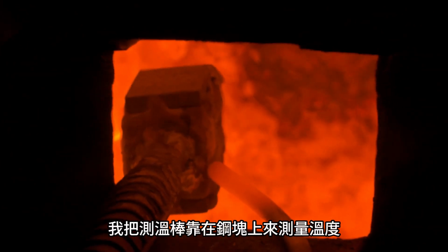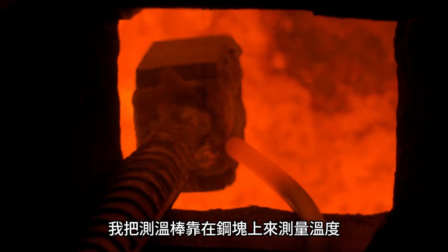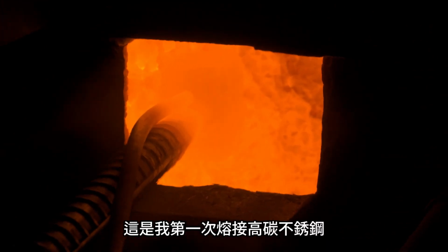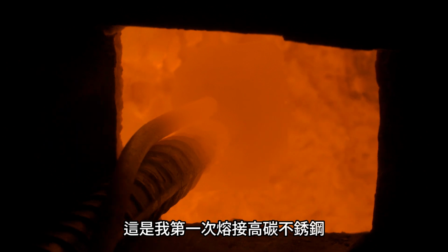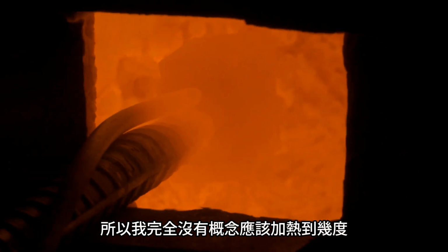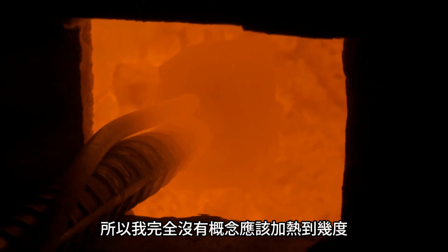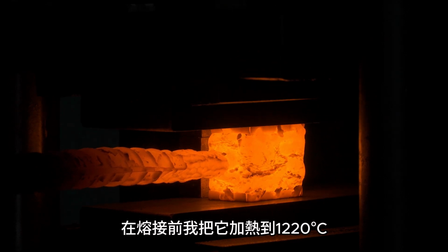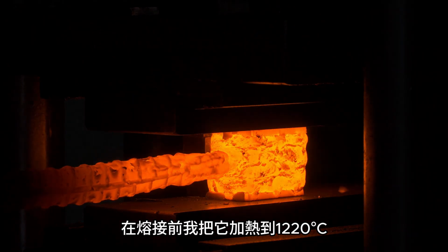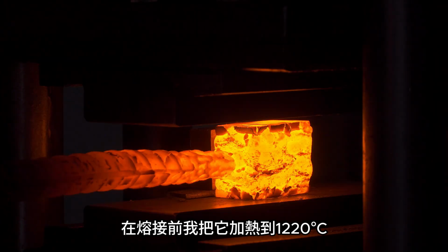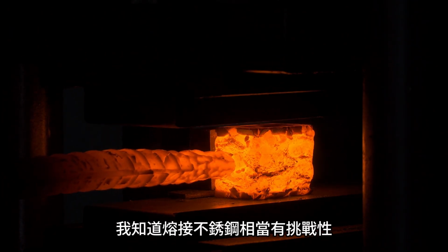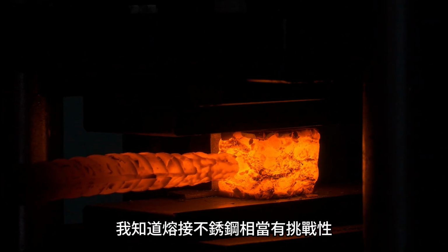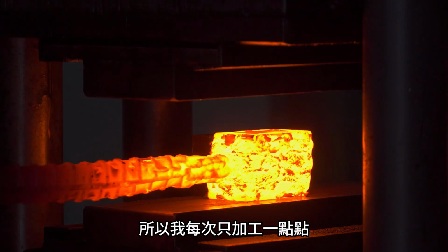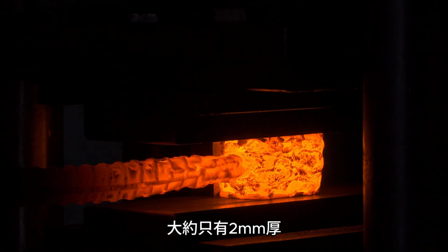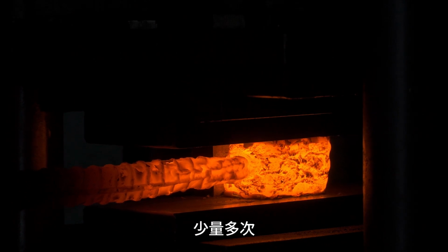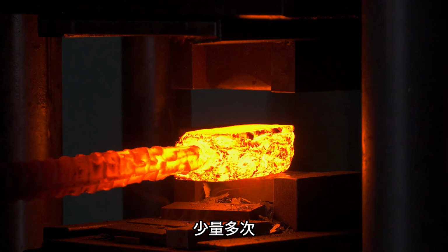I place the thermometer against the billet to measure temperature. This is my first time forge welding high carbon stainless steel, so I had no idea what temperature to heat it to. I ended up heating it to 2230 Fahrenheit before starting the weld. I know that welding stainless is very challenging, so I pressed down a little bit at a time, about 0.08 inch thick, repeating the process multiple times.